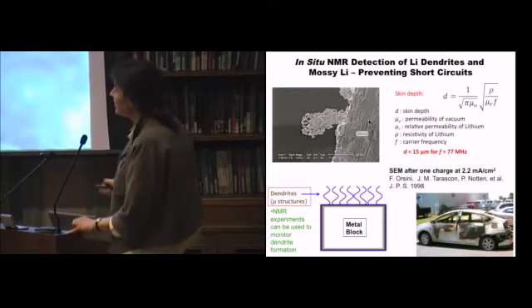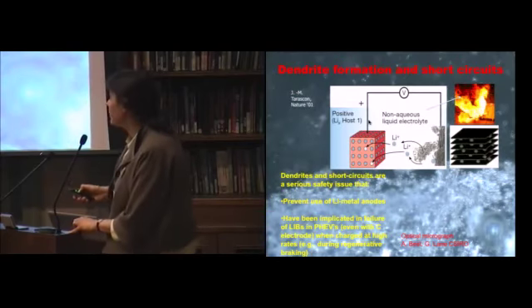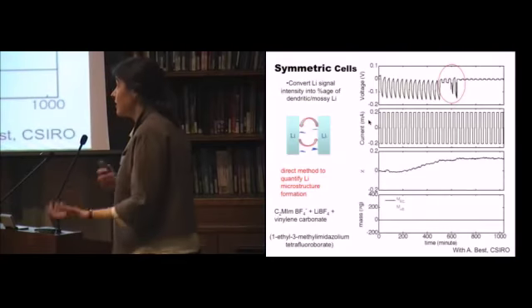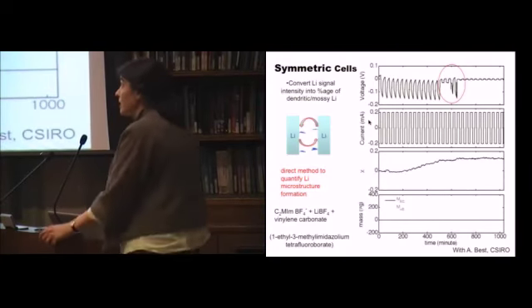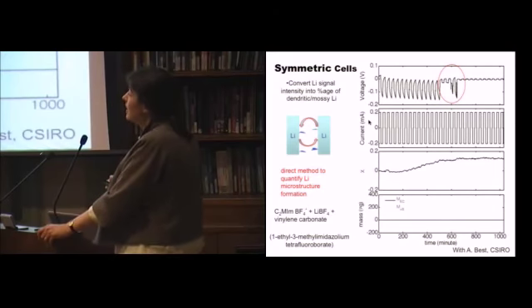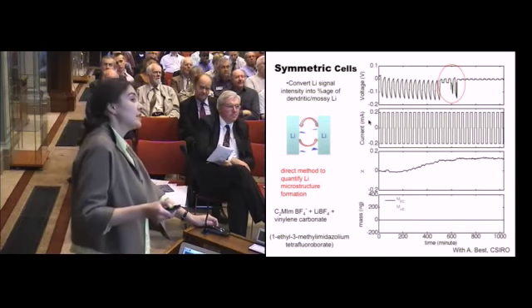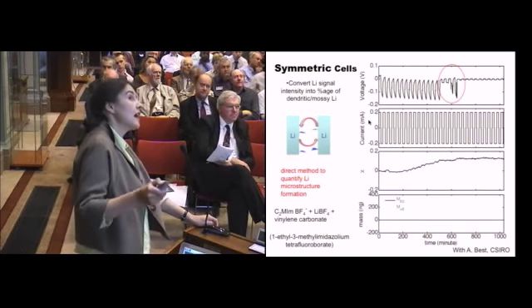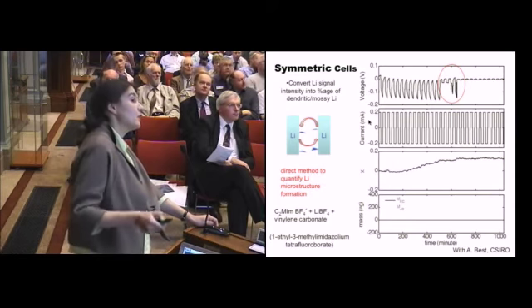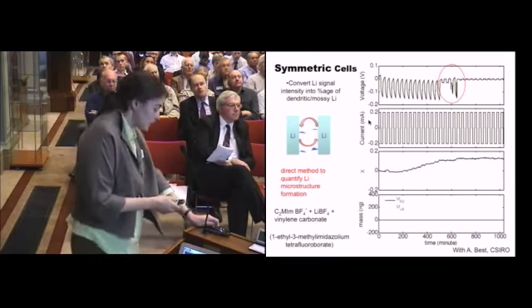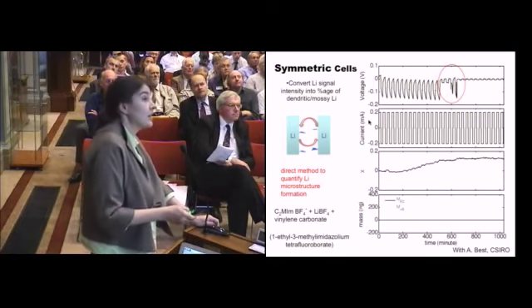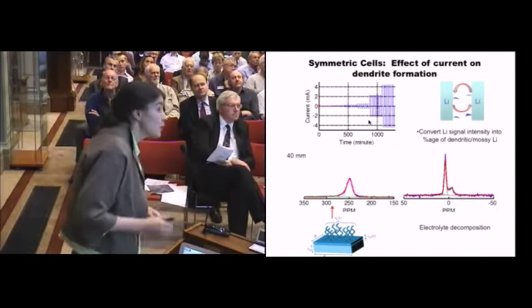And just to remind you, it's these dendritic structures that can be serious safety issues. So what I can do now is devise a way for testing electrolytes to see which ones are good for dendrite formation. This is one where I've just replaced the electrolyte by a so-called ionic liquid, and I'm cycling backwards and forwards with constant current. So here's the experiment, backwards and forwards, and you can see it fails here, where you form a dendrite, and you can use the NMR to track and see the formation of the dendrite before it actually appears in the electrochemistry.